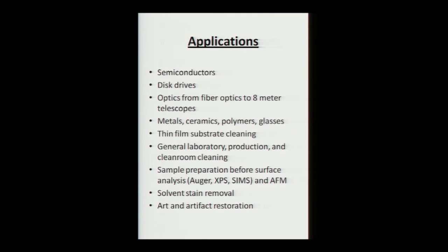Those methods, Auger, X-ray photoelectron spectroscopy, and SIMS, they're used to analyze the first 10 or so atomic layers of a surface. So cleanliness is critical. And that's where I got my first experience in CO2 snow cleaning, and we published showing it was effective at that scale. Then the last one, AFM, atomic force microscopy, and we'll show a good example of that later.